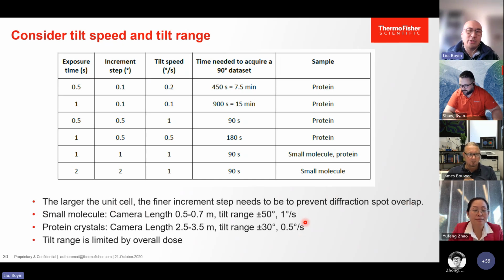So basically, we have some general, very general suggestions. For small molecules, camera length 0.5 to 0.7 meters, tilt range plus minus 50. You can tilt faster, 1 degree per second. With protein crystals, a longer camera length, because you have so much information there. You want to separate the information, so you have to lose some high resolution signals. You can use camera length 2.5 to 3.5 meters, tilt range plus minus 30, 0.5 degrees, and tilt slower.